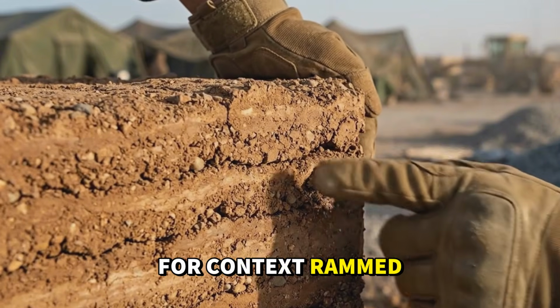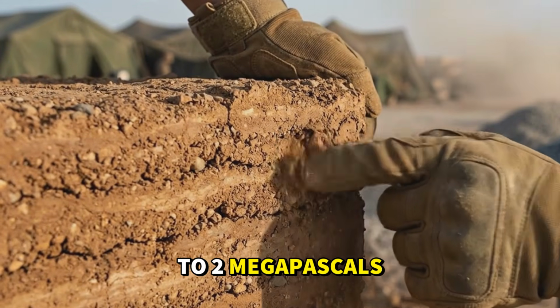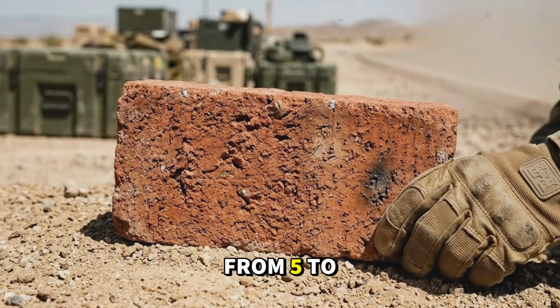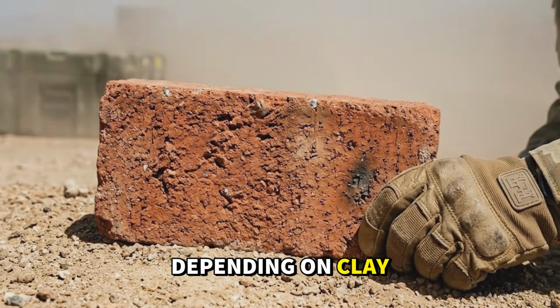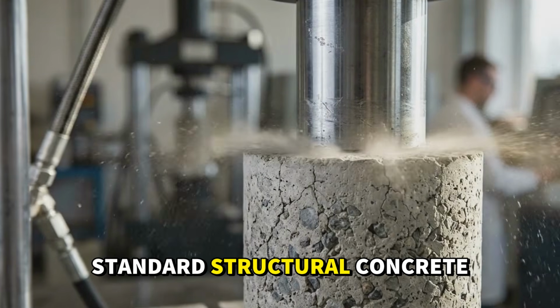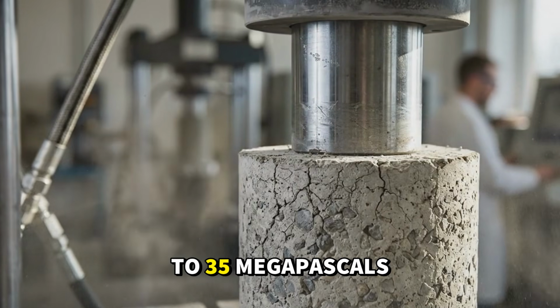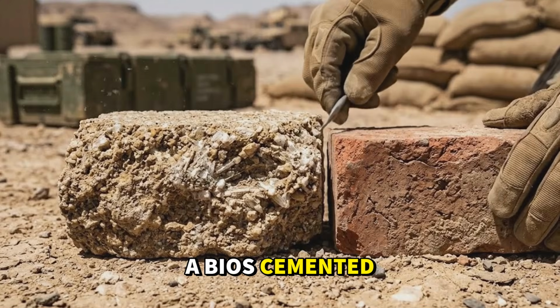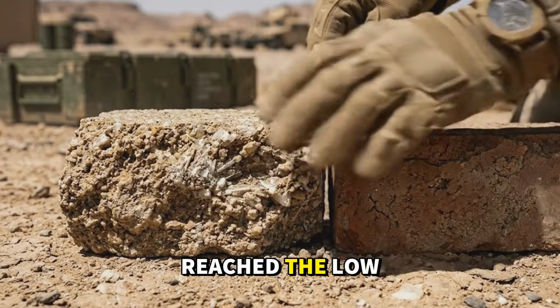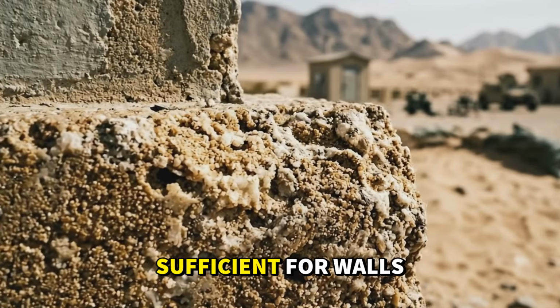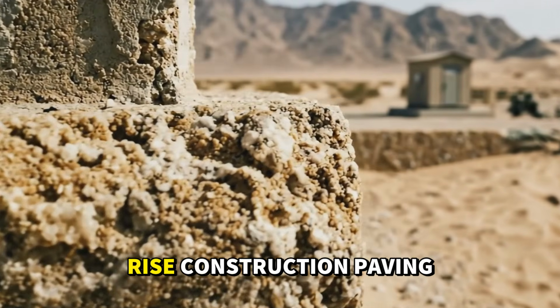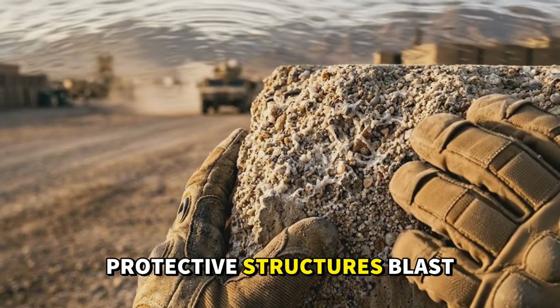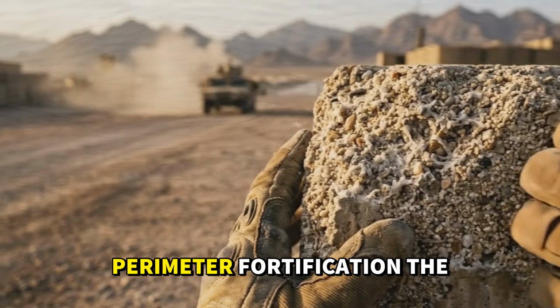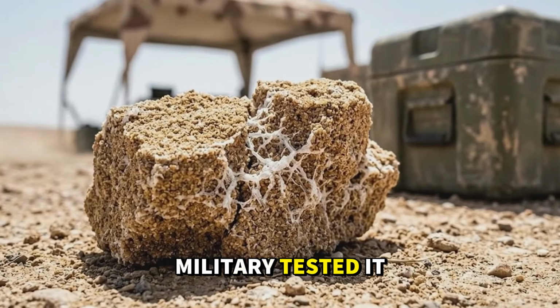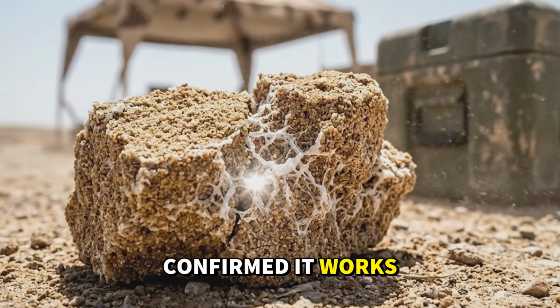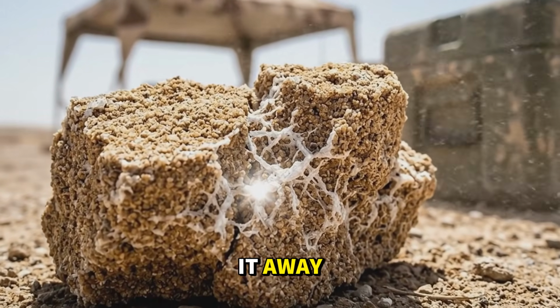For context, rammed earth averages 1 to 2 megapascals. Fired brick ranges from 5 to 20 megapascals depending on clay and firing temperature. Standard structural concrete ranges from 20 to 35 megapascals. Bio-cemented sand with adequate treatment cycles reaches the low end of fired brick, sufficient for walls, foundations and low-rise construction, paving, protective structures, blast barriers, perimeter fortification. The military tested it, published the data, confirmed it works, and then filed it away.